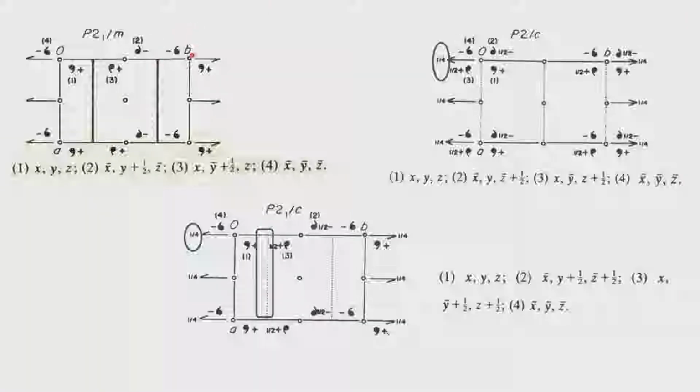In other words, whether it is a two-fold axis operation or a mirror alone or a combination of 2 and m, whether it is a 2-1 by c operation, all these symmetry operations are restricted to operate only along the y direction, and that is why it is called a unique axis in a monoclinic system, and that B axis therefore is the one which shows the presence of the two-fold along with it.